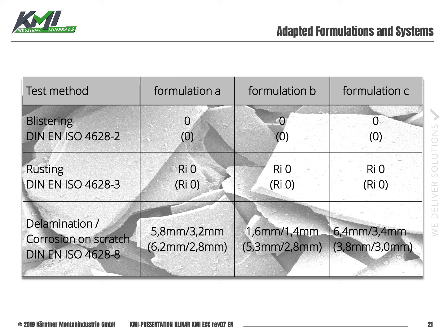Here you can see the test results. We tested blistering, rusting and delamination around the scratch. Again, after this 25 weeks cyclic corrosion and weathering test. Formulation A, just to remember, is the standard. Formulation B is with a lower loading level of micronized MIOs, and formulation C is the same loading level but a thinner film for the MIO based coating. And you can see the test results are absolutely comparable. That means blistering, rusting and delamination are more or less similar.